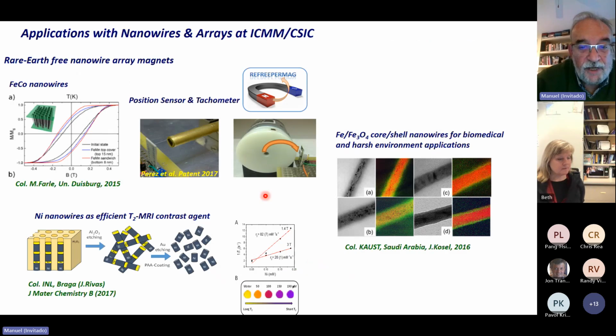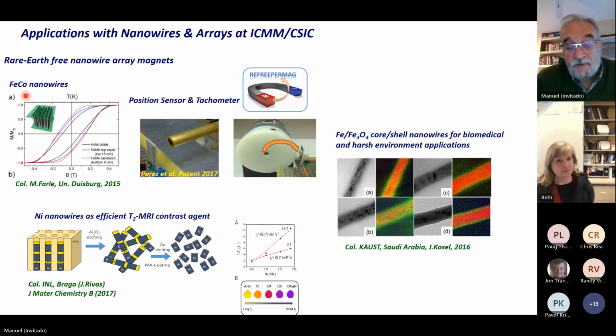In our group, we have also tried to make use of the magnetic properties of the nanowires, arrays of nanowires for some applications. For example, in another European project, we developed iron cobalt nanowires and their arrays without rare earth. The objective was to produce rare earth-free nanowires. In fact, iron cobalt, in a composition 35 to 65, has the largest saturation magnetization of 2.2, 2.3 Tesla.